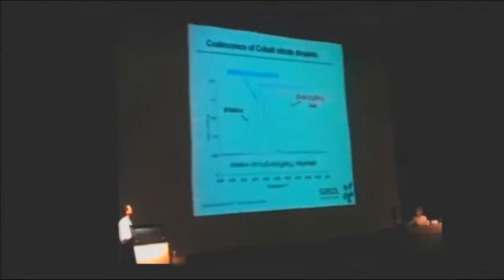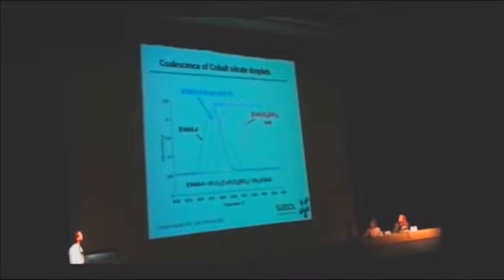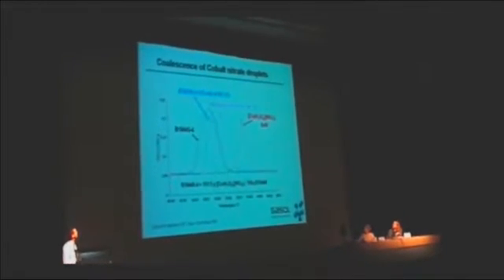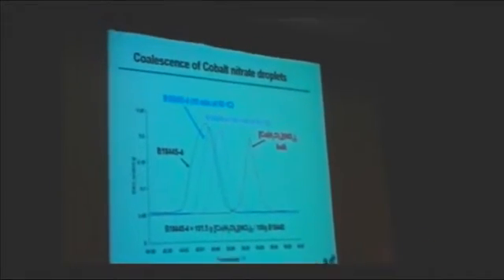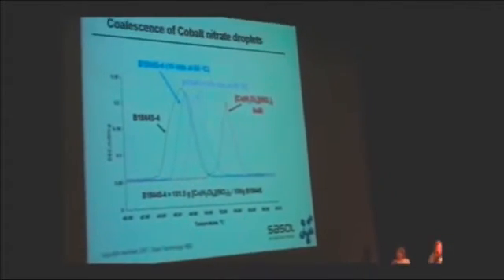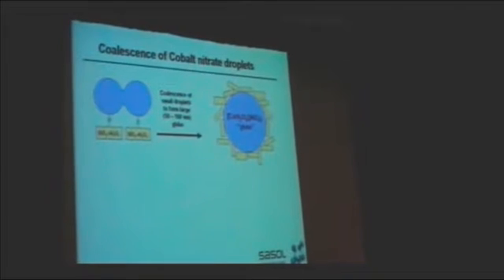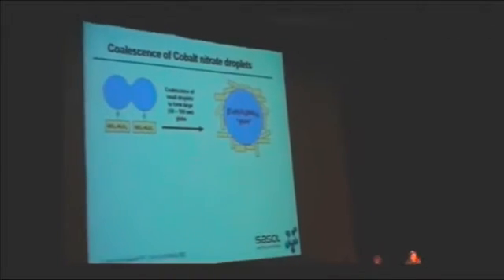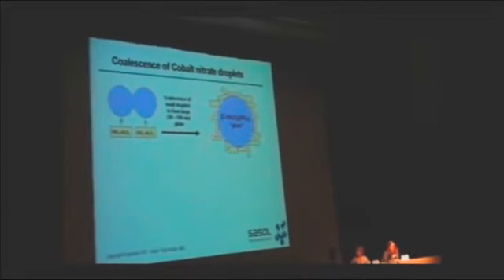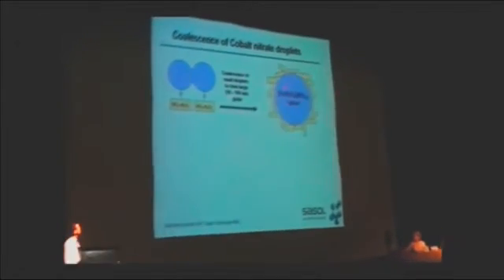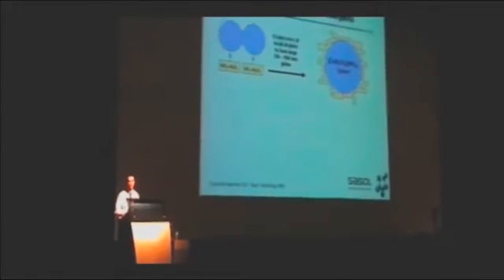When you do repetitive cycles, in other words, you keep the material at elevated temperatures, 65 degrees Celsius, for extended periods of time, you see that upon cooling and re-recording of the spectra that peak maximum starts drifting towards bulk phase cobalt nitrate character, giving us a clear indication that coalescence of cobalt nitrate droplets is most probably taking place. And it keeps on taking place until you reach some critical size, which seems to be between 50 and 100 nanometers in size, where the process stops.